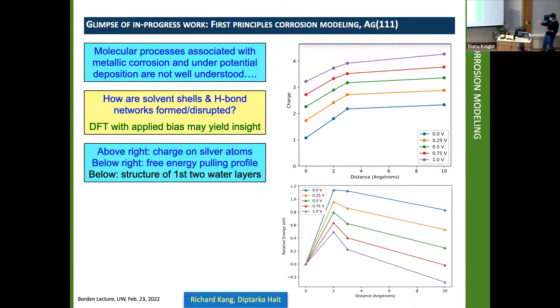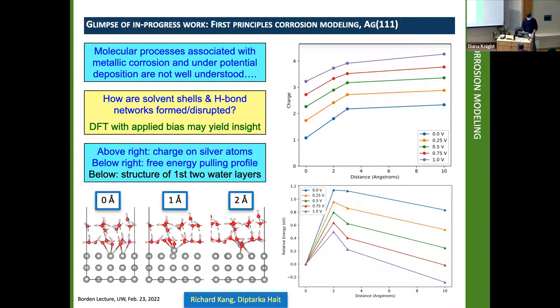So this basically says that corrosion becomes thermodynamically spontaneous, kinetically inhibited. And then the kind of data that we're just beginning to acquire is here, showing you how the water layer is changed as you begin to pull out a silver atom and turn it into a silver ion. As you turn it into a silver ion, it will become solvated and will develop a characteristic local solvent structure that's well understood when the ion gets well away from the electrode. But this transition is what's especially interesting.